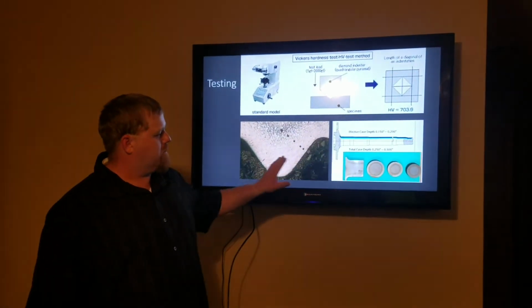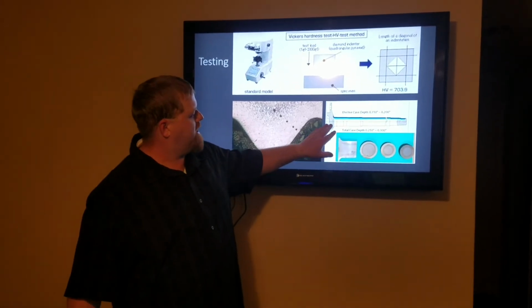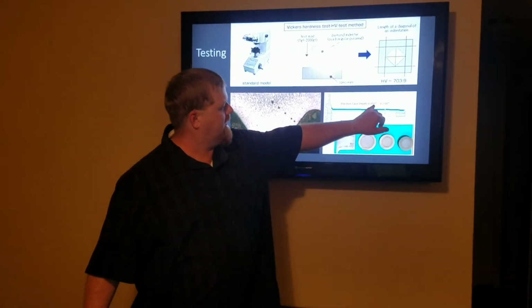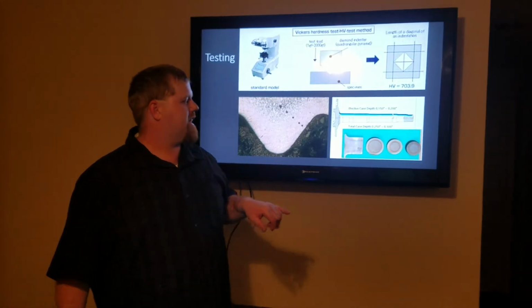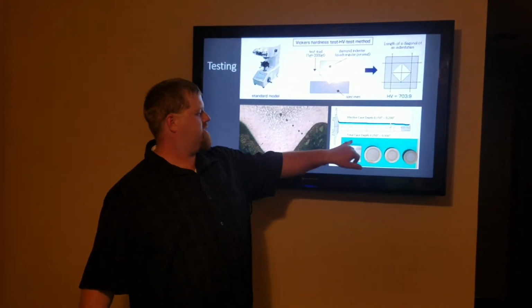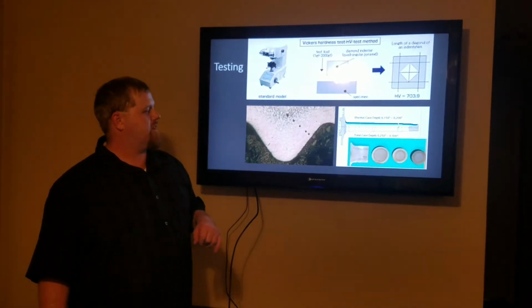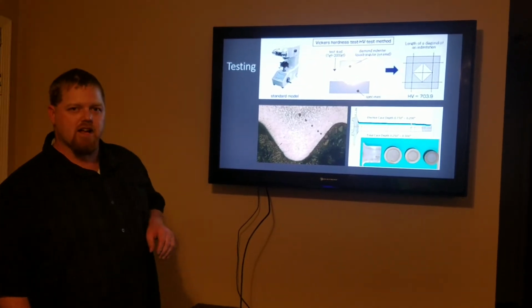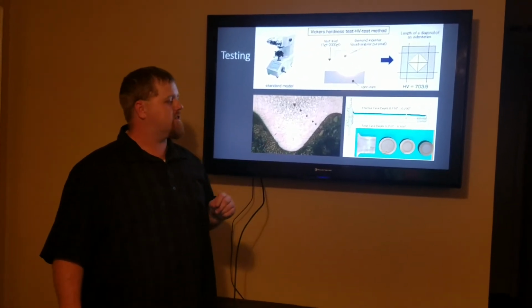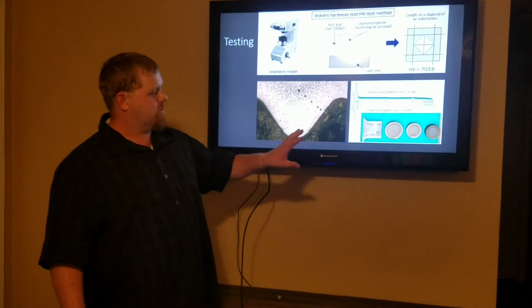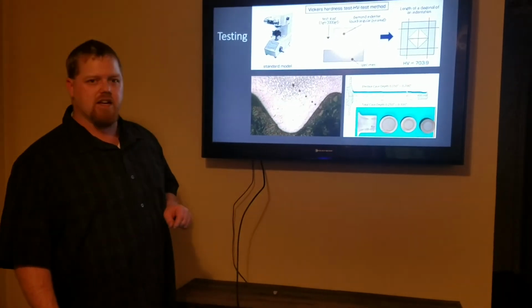On a part similar to the one we just saw in the scanning operation, you can see an effective case depth they needed of 150 thousandths to 200 thousandths of an inch, and a total case depth of 250 thousandths to 300 thousandths. They keep a tight tolerance with induction hardening, and it's awesome the way they can do that and the way we use these things to do that.